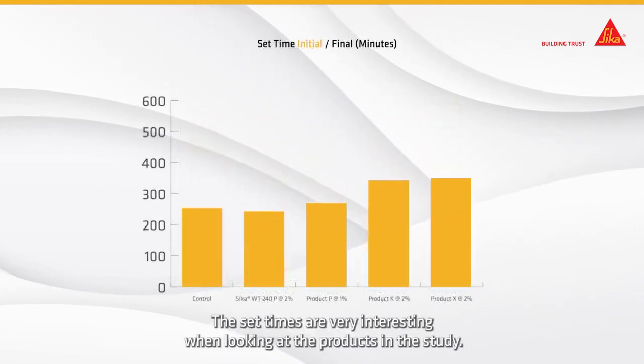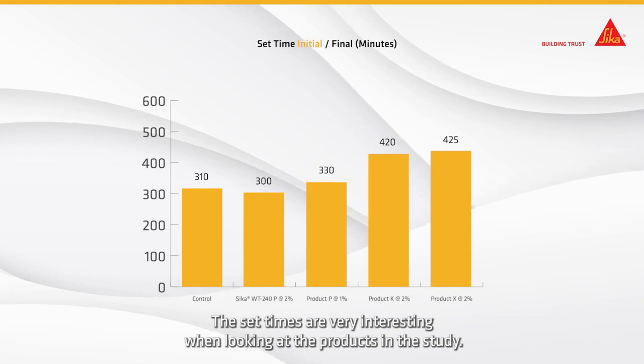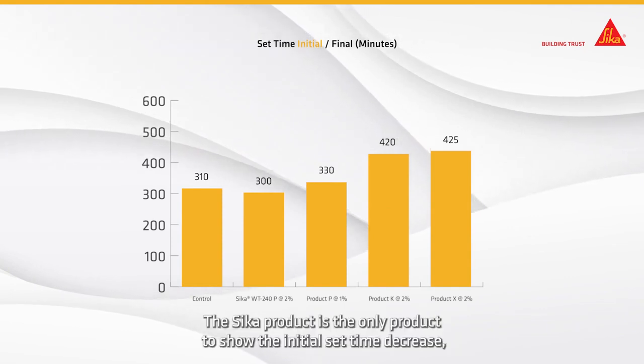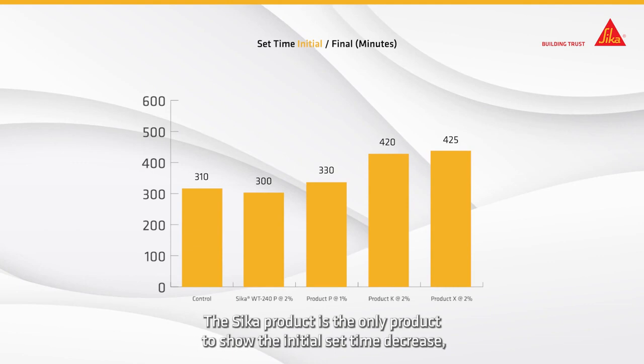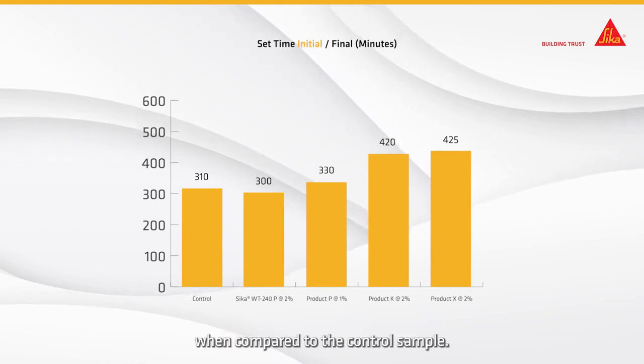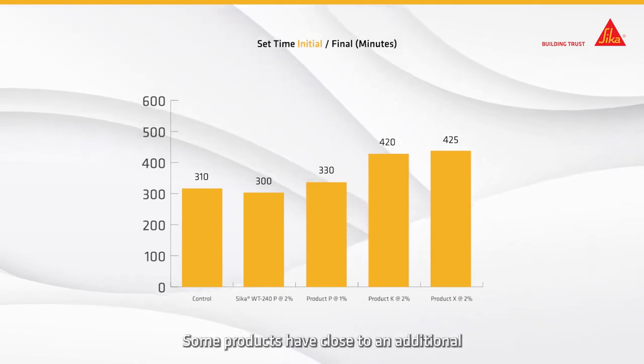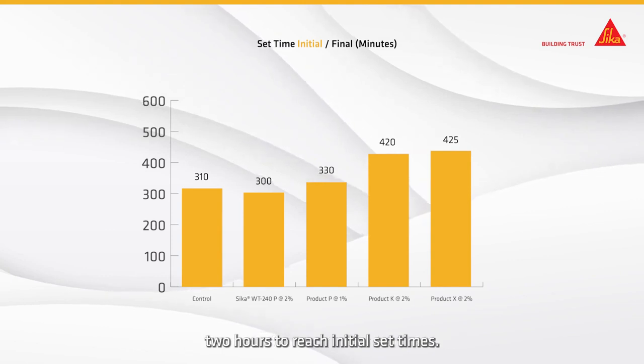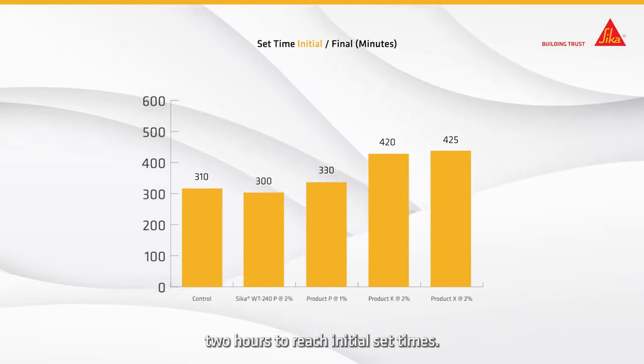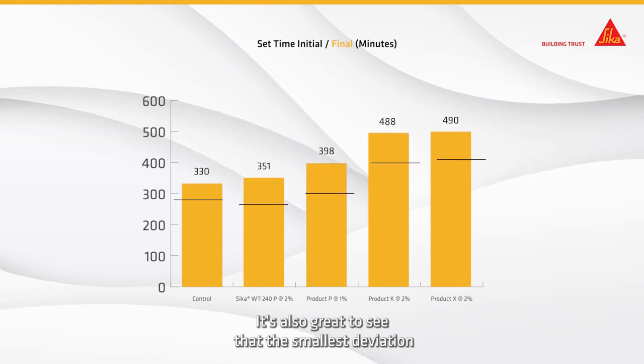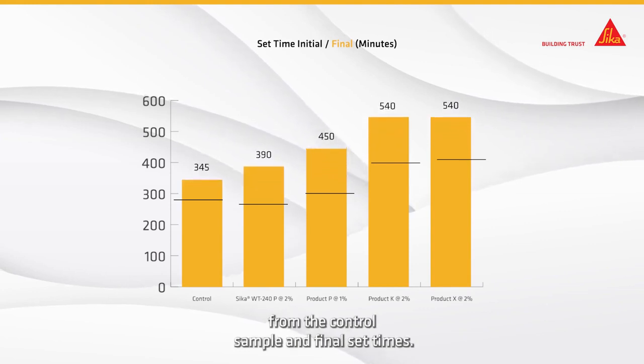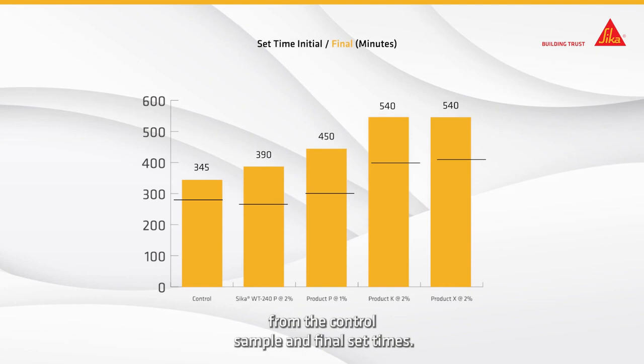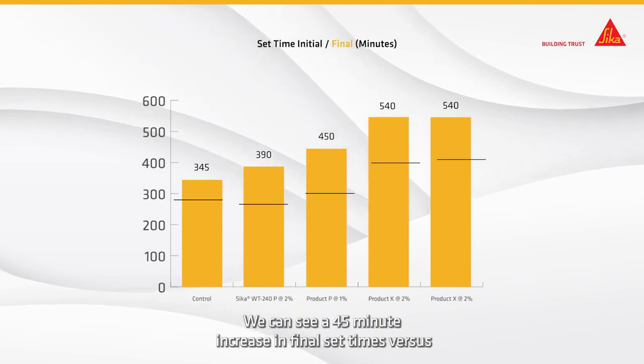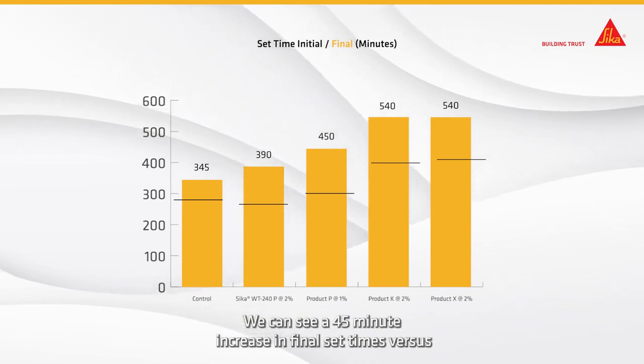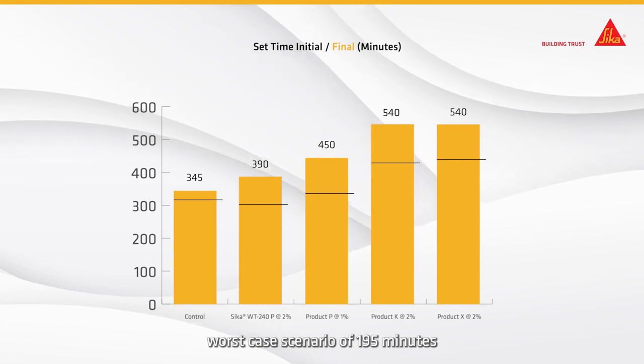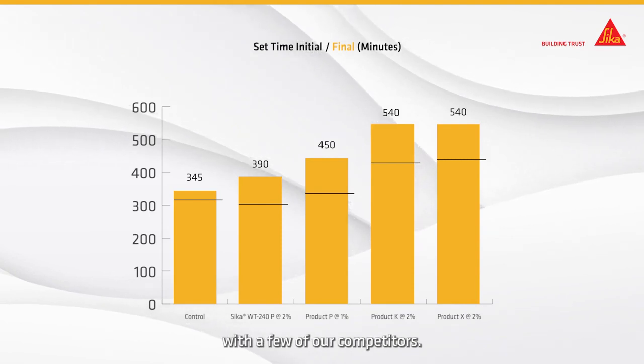The set times are very interesting when looking at the products in the study. The Sika product is the only product to show an initial set time decrease when compared to the control sample. Some products have close to an additional 2 hours to reach initial set time. It's also great to see the smallest deviation from the control sample in final set times. We can see a 45-minute increase in final set time versus a worst case scenario of 195 minutes with a few of our competitors.